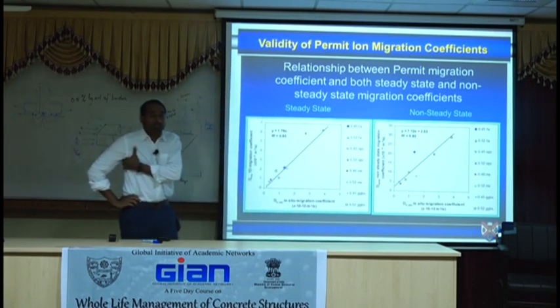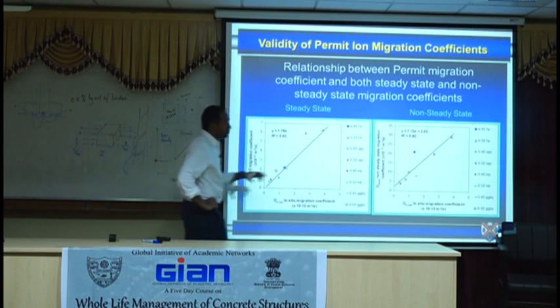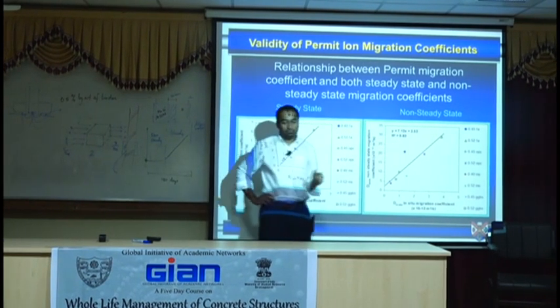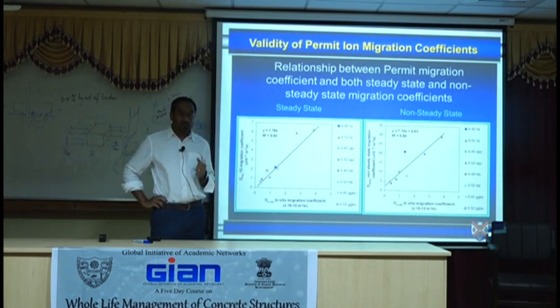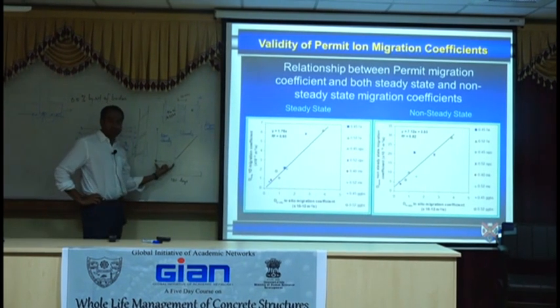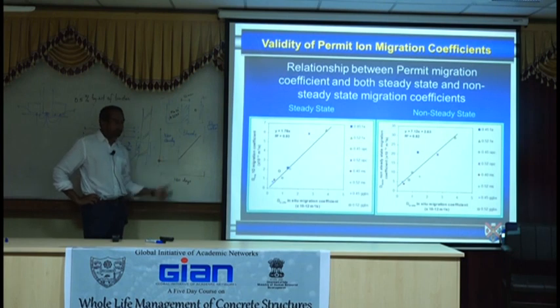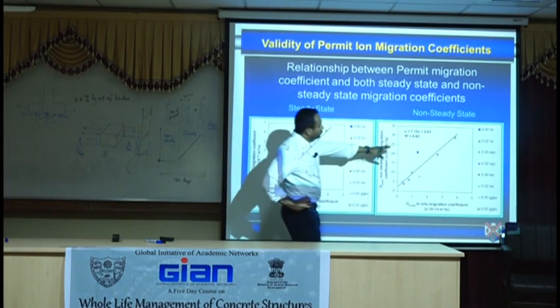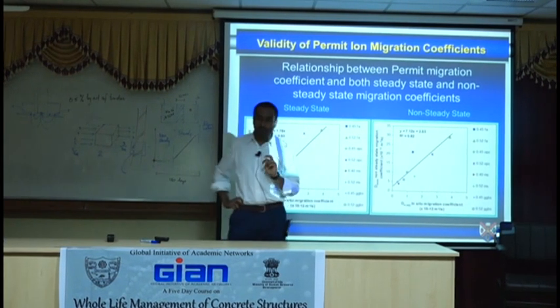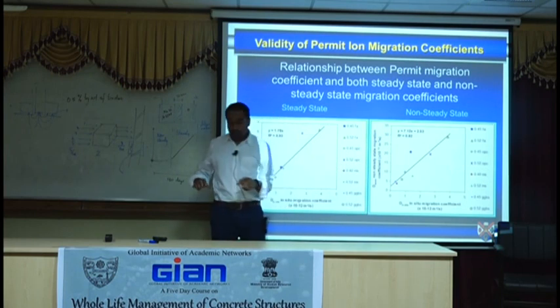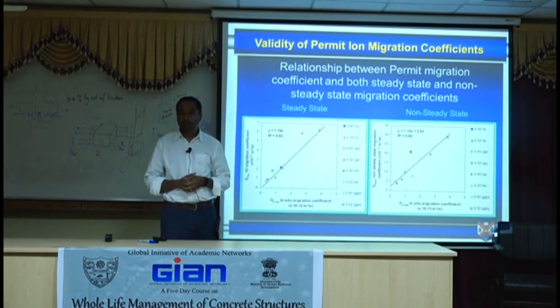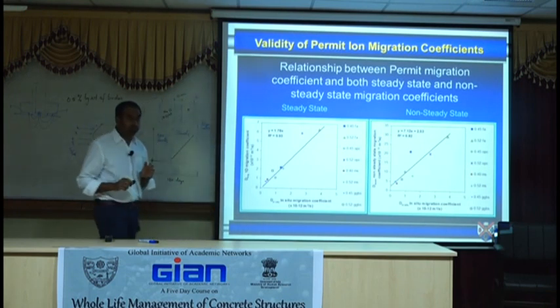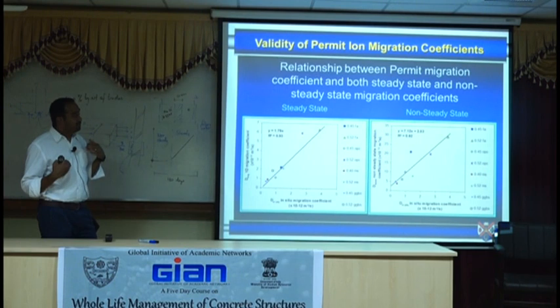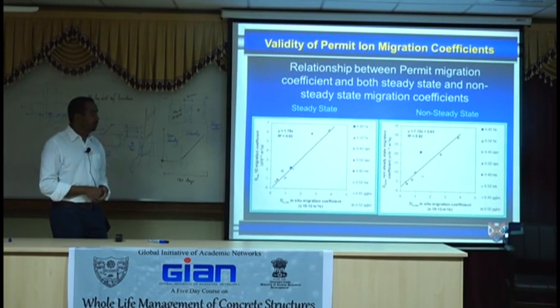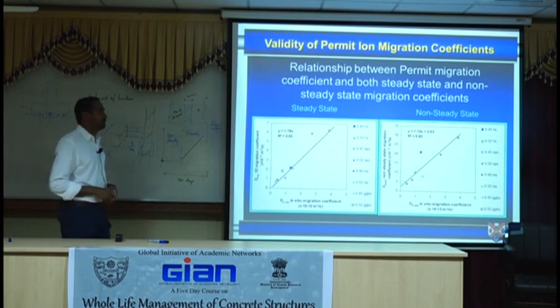But it does correlate reasonably well. And I know the correlation will drop. That will drop if you're using high volume replacement. If you're using concrete with extremely high binding capacity, it'll drop. That is to be expected because extreme binding capacity means this period will be dominant. Okay. You should also note that the correlation is significantly favoring the non-steady state test because the coefficient there will be much higher than steady state. It's to be expected. Okay. So that's how, if you're going to develop a test yourself, this is what you need to do to prove that our test is better than others or our test is as comparable as others.